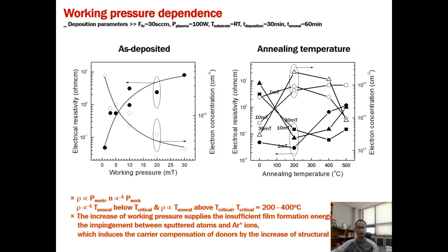We can say that the increase of working pressure supplies insufficient film formation energy due to impingement between sputtered atoms and argon positive ions, which induces the carrier compensation of donor by increase of structural imperfection.